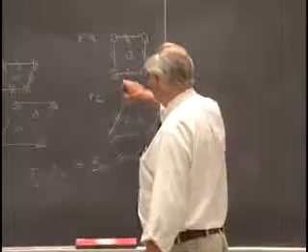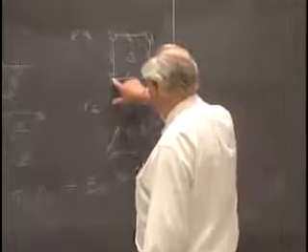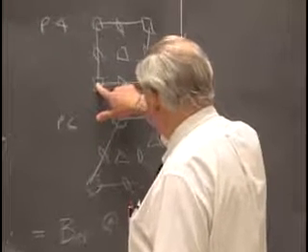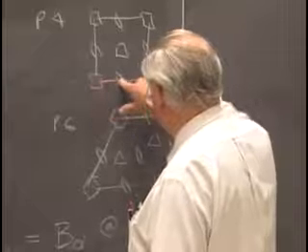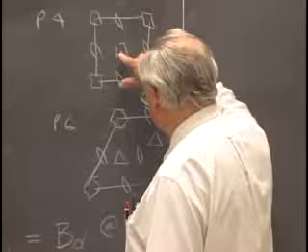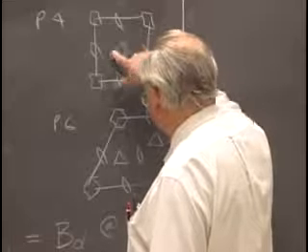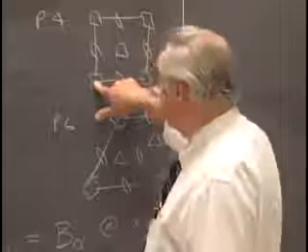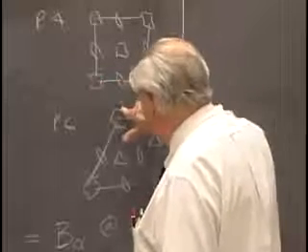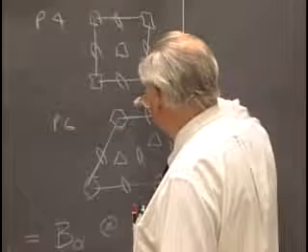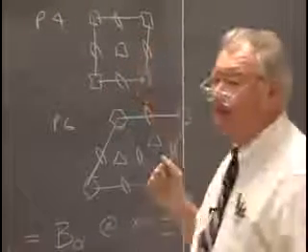So for example, if I combine the fourfold axis with a translation, the 180-degree operation that's present in a fourfold axis puts b pi here. The 90-degree rotation puts b pi over 2 here. And the 270-degree rotation, which I can define just as well as a minus pi over 2, puts the operation a minus pi over 2 down here. So it's not an equation in symmetry elements. It's an equation in individual operations.